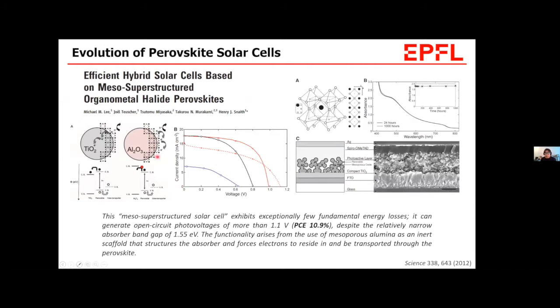And in this work, instead of mesoporous titanium dioxide, an insulating mesoporous scaffold of alumina was introduced. And this increased the VOC compared to the device using sensitized mesoporous titanium dioxide. The authors claim that the photo-generated charges can stay longer without recombination. This can increase the VOC, they claim.